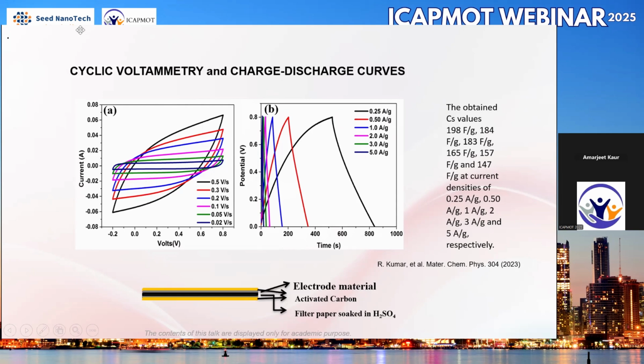Then we did the galvanostatic charge discharge measurements, which are almost symmetric, as you can see here, and they are done at different rates in terms of the current, that is 0.25 amperes per gram, 0.5 amperes per gram, and so on. From this we calculated the specific capacitance, that is the capacitance per unit gram, and the maximum we have got is 198 farad per gram. This is a very good capacitance for industrial application of the capacitor.